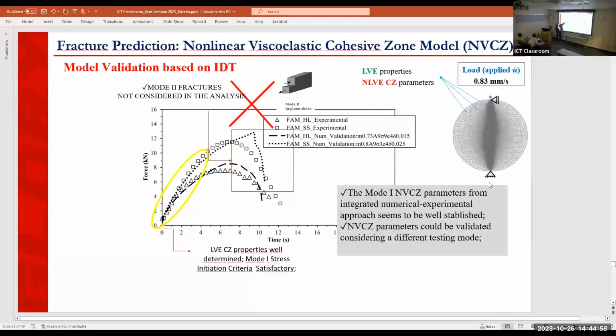The initial slope was an indicator for us that the linear viscoelastic properties were satisfactorily obtained. We didn't get a good match after the peak. For us, that could be an indication that in IDT we have mixed mode cracking being developed, not only mode 1, and in this simulation we didn't consider mode 2 cracks. That could be a reason for not having a good match on the post-peak curve.